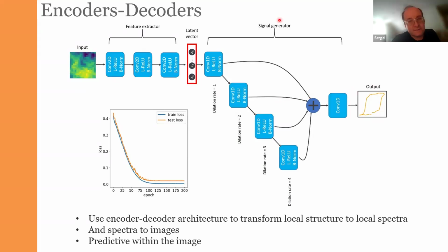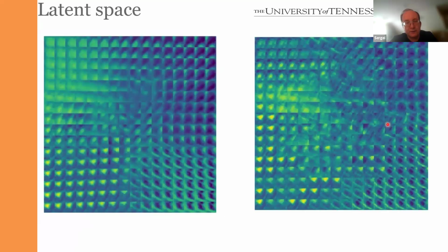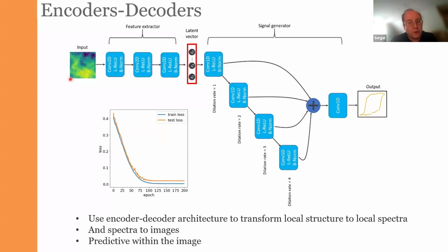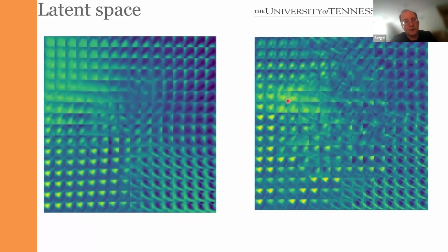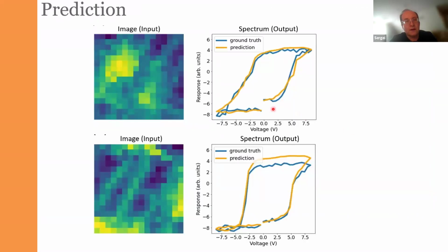So it is very natural to extend the VAE approach to the encoder-decoder, where we encode one type of data, and then we take this encoded latent vector and decode it into the paired output. So for example, this is the example of the input domain structure, output the hysteresis loop. So if we train the network like this, we essentially learn a correlative relationship between the local structures and local spectroscopies. The way that we examine the structures is through the same latent spaces, so there is nothing unusual here. Interestingly enough, this approach works remarkably well.